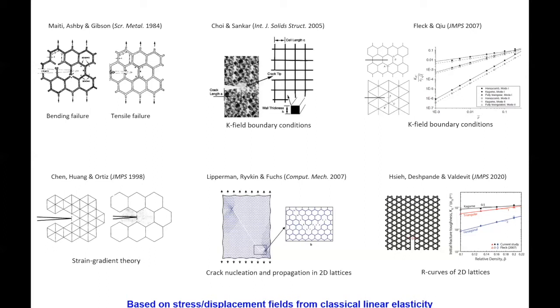So the question is, for us, what happens if you don't think that that's the stress field ahead of the crack? Whether because your lattice is more exotic, maybe not stress dominated, or maybe because you just don't have infinite cells and a very, very long crack, right? You can think about the specimens that we had before. What if you have 20 cells, right? Is that still a material? Can you have a definition of toughness there? So it's both a theoretical and philosophical, but also a very applied question.